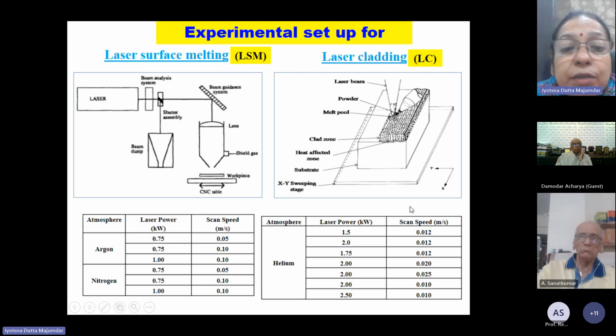This is a typical laser surface processing where we used argon and nitrogen as media, and the power was varied; these are the optimum parameters. One interesting observation on laser surface processing is that you get very good results only when you process under a very narrow regime, meaning narrow laser power and scan speed combinations. Viewers often ask why we didn't choose higher power and lower scan speed. But in all cases, even if you use thousands of parameters, you get the best result only under a very narrow power and scan speed combination regime. It's not power, rather power density, or rather a narrow energy density regime.